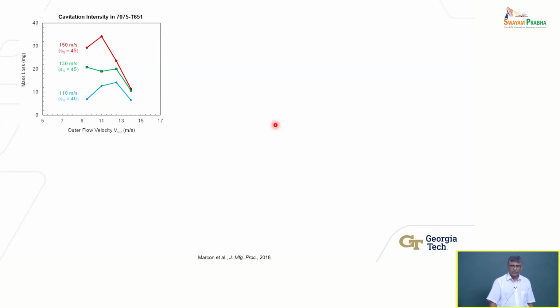All right, so it's easy to measure mass loss. I can just take a scale. I can measure the starting mass. I can then expose it for a certain period of time and then measure it again, see how much mass was lost. That tells me under these conditions this is what happened to the material, right? So this is what we did as a function of the flow velocities. This is the outer flow velocity, and this is the inner flow velocity, right? And this is the mass loss in milligrams of, in this case, aerospace grade aluminum, 7000 series aluminum.